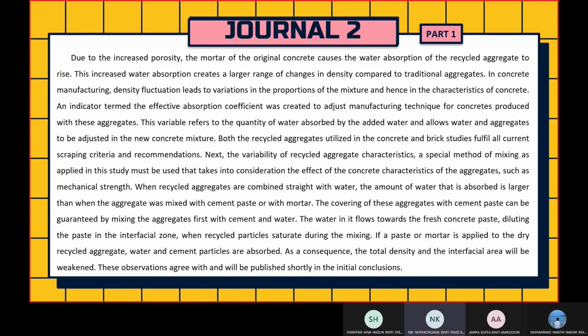Discussion for Journal 2. Due to the increased porosity, the mortar of the original concrete causes the water absorption of the recycled aggregate to rise. This increased water absorption creates a large range of change in density compared to traditional aggregate. In concrete manufacturing, density fluctuation leads to variation in the proportion of the mixture and hence in the characteristics of concrete. An indicator term, the effective absorption coefficient, was created to adjust manufacturing technique for concrete produced with this aggregate. This variable refers to the quantity of water absorbed by the added water and allows water and aggregate to be adjusted in the new concrete mixture.